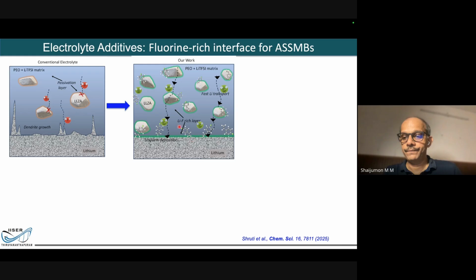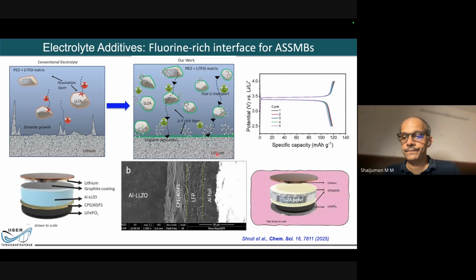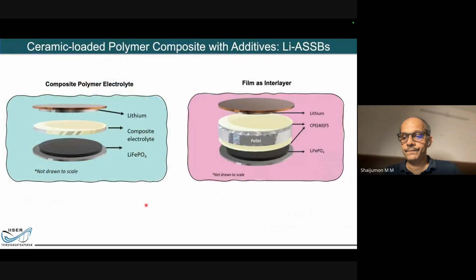And that green layer is basically a lithium ion-rich layer, sort of lithophilic in nature. That attracts the lithium, and this kind of dendrite formation is sort of killed, right? So that ends up in getting some very interesting results. These are all devices that we make. In fact, this is the polymer composite electrolyte that I talked about. It's a solid compartment, and it is sandwiched between an anode, which is lithium, and a lithium iron phosphate cathode, right? And it forms a completely all solid state device, I would call it. No liquid electrolyte is added here, sorry.